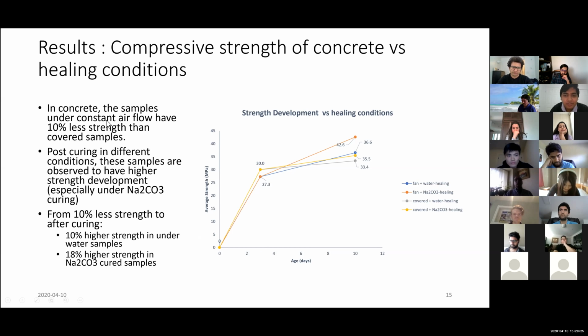And similarly, that was for mortar. Then I did the same test again for concrete. In concrete, the results were not so starkly different. So I observed a loss of around 10% of strength even after 3 days of exposure, and after curing for 7 further days, we can see that sodium carbonate healing is performing better in this one as well as in the covered samples, but overall the damage itself is not that much in concrete. In concrete, since there is internal curing as well, and since there are aggregates as well, it might help reduce the shrinkage coming from a constant flow of air.